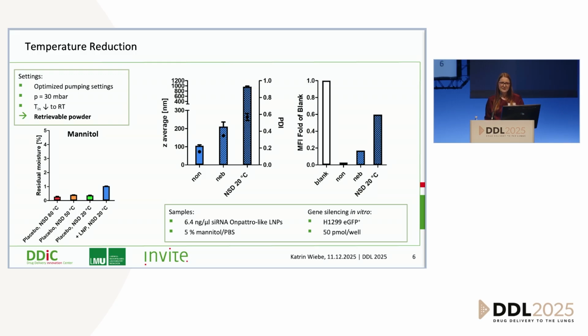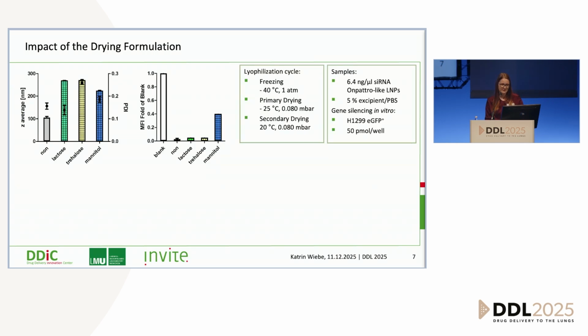So what else is there that is happening to the LNPs? And one actually quite obvious thing is the drying itself, because we don't only nebulize and then heat treat these things, we also take away the water that actually also stabilizes our particles. And if I want to dry particles without adding any shear stress or heat, I can lyophilize them, and this is what I did. And you can see that I use different formulations to find out what impact of the drying formulation I have.